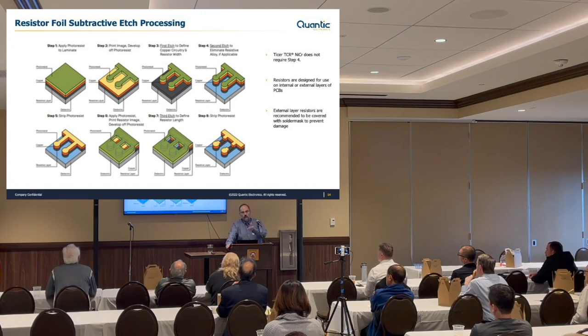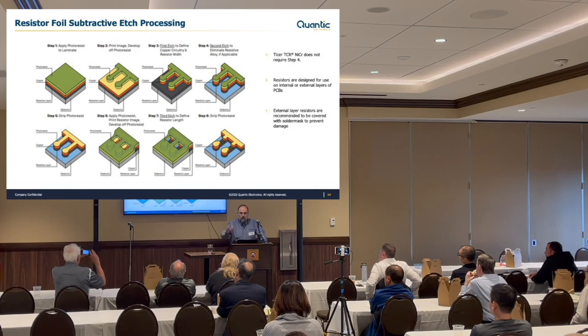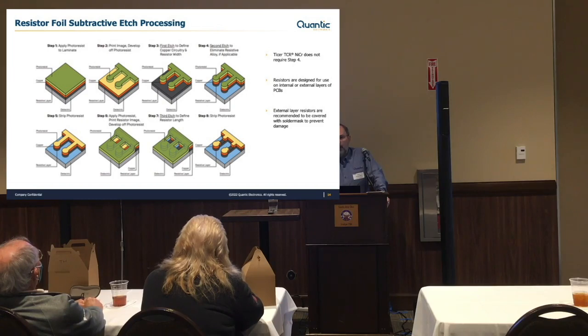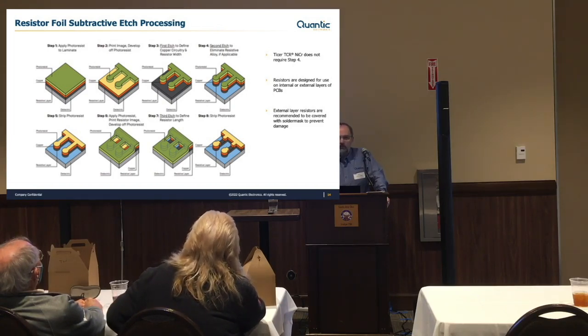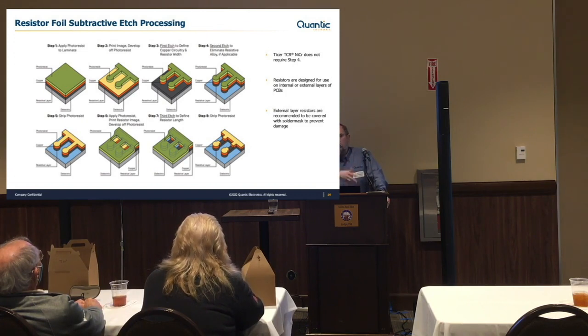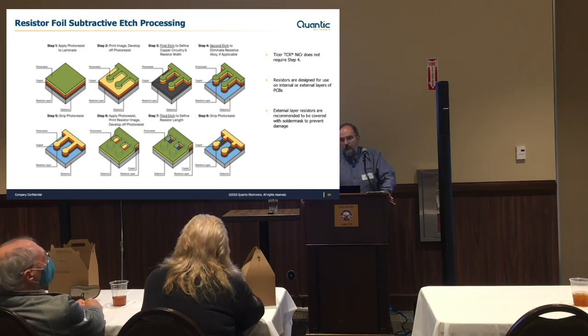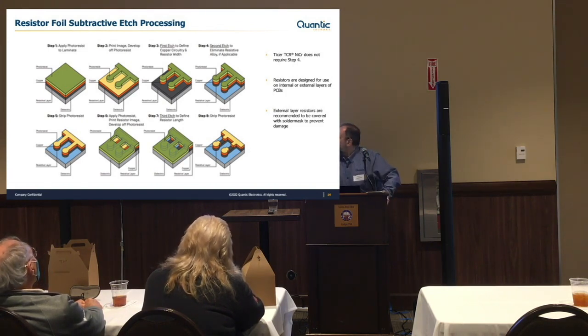With the nichrome that comes from Ticer, it's thin enough that typically your standard copper etch process will remove it. That's one of the benefits of the Ticer over the Ohmega, because it is much thinner and it's easier to get rid of. But then you go through and do a secondary imaging process where now you want to get rid of the copper where you want the resistor layer to be. So you laminate it again, do the photoresist process, but this time you do an alkaline etch, because the alkaline etch will remove the copper, but it won't affect the resistor layer. So the first step is a cupric etch, the second one's an alkaline etch, which everyone has, because that's your outer layer etch, and it is typically alkaline. Then you strip the resist, and now you have your resistors defined.